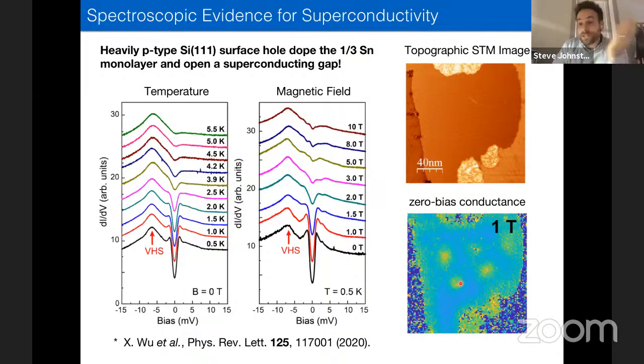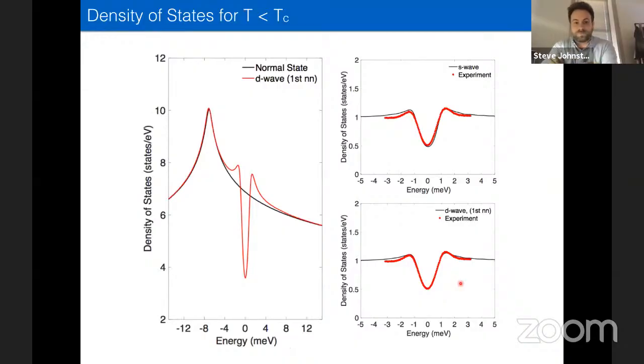So then the next question is, okay, what's the symmetry of the order parameter? One way to do this is to try to actually fit the spectra with various symmetries. There's a number of options. This is a theory model calculation now. What's shown here in black is just the normal state density of states from the non-interacting band structure. And then the same thing if I put in a d+id order parameter by hand, with a magnitude that's just a number that I put in by hand.